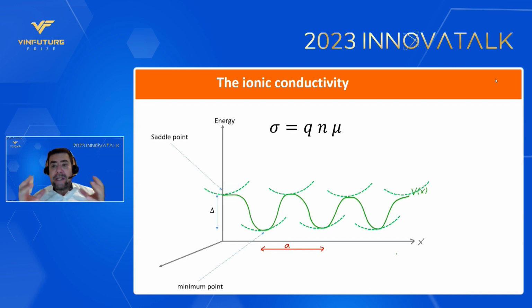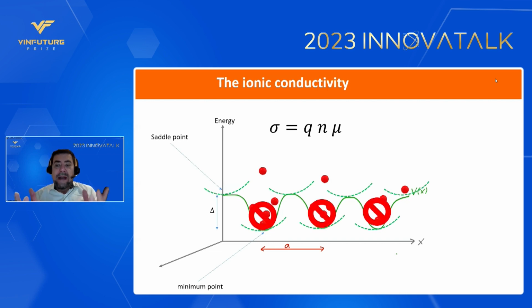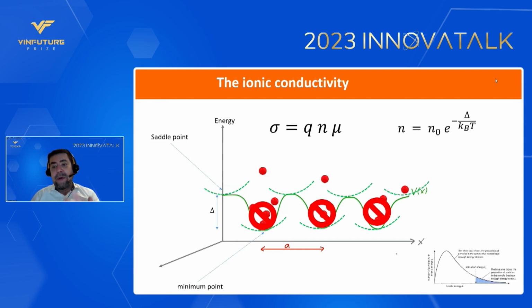A crystal is a periodic system. So there is a potential that is seen by the lithium atoms, and this potential has minima, maxima, and saddle points. So for a lithium atom to move inside of a crystal, it has to go from one minimum to another. By doing what? By jumping over these saddle points. So if the energy of the lithium atom is too small, it becomes blocked around the minima of the potential, so it cannot move. So only the lithium atoms that have thermal energy above the saddle point energy are the ones that can move. So only a tail of the thermal distribution actually contributes to the conductivity. The number of ions depends exponentially on the temperature. So it's a very simple explanation for the exponential dependence.